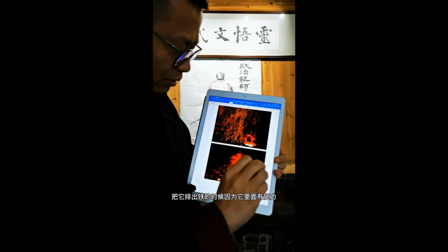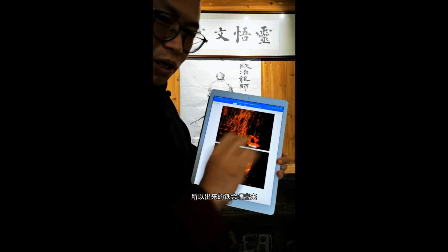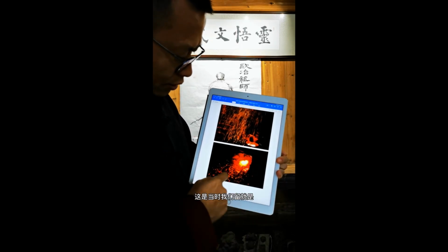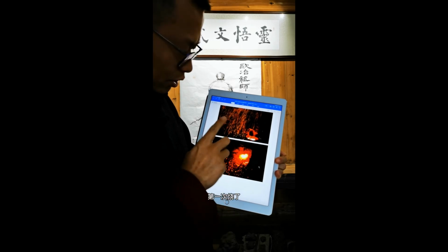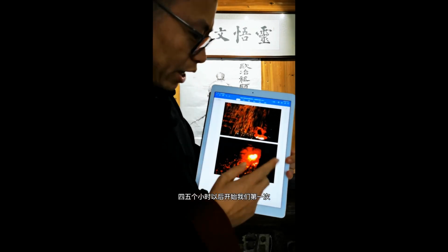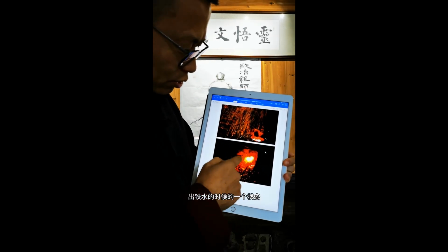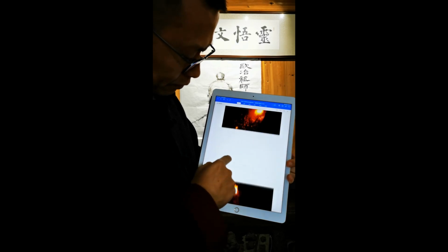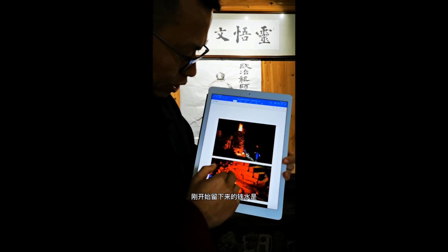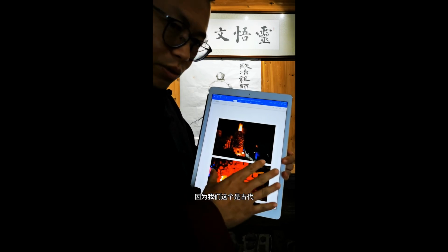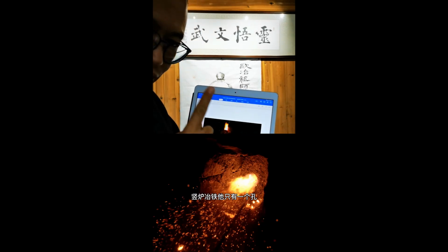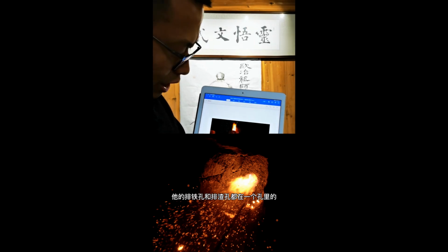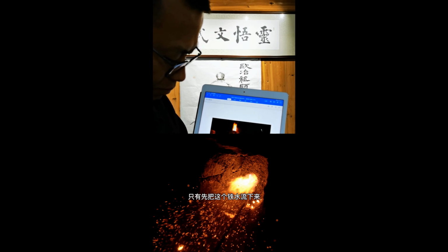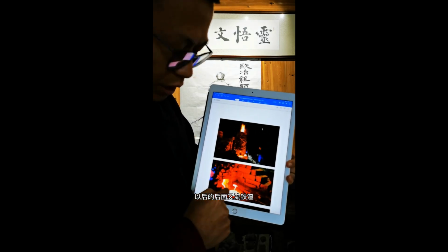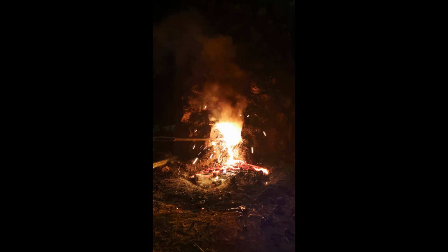This is how we got the iron out of the furnace, because there's pressure in the furnace. That's why the melted iron would squirt out. It's a very strong squirt. After 5 hours of burning, this is how the molten iron came out. The molten iron began to flow because there was only one hole, as in ancient times. This hole is for the melted iron to flow out, as well as for the slag hole.